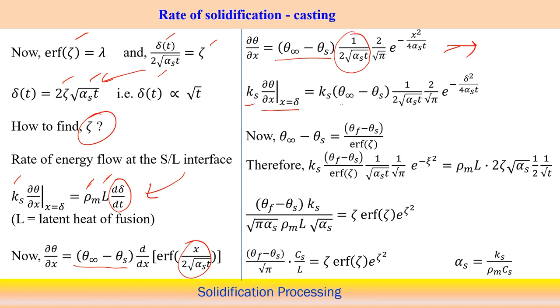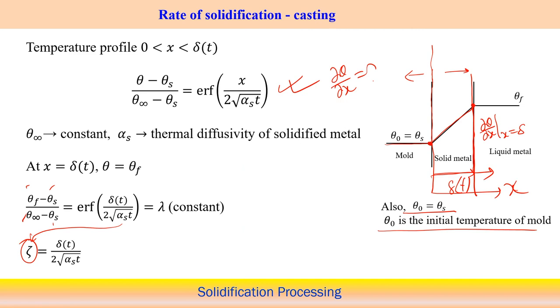We are getting k s into del theta by del x. We can further modify at x equal to delta, then we are getting 1 by 2 root alpha s into t into 2 by root pi into e to the power minus delta square by 4 alpha s into t. So, then the 2 will be balanced, and theta infinity minus theta s we can also calculate in terms of the error function zeta, because in the first equation, theta f minus theta s, theta infinity minus theta s is equal to the error function of this, that is the lambda constant, or this is actually zeta. So, here it is basically equal to the error function of zeta.